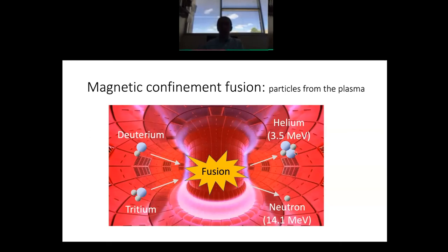But the neutron, which comes out at 14.1 megaelectron volts, flies right through the plasma and impinges upon all of the solid components that are facing the plasma, and indeed penetrates quite deeply. And in fact, that's exactly where we intend to get the energy out of our fusion reactors, from those neutrons. So the materials, of course, get damaged in the process. And so that's another way the materials become damaged in technological situations.